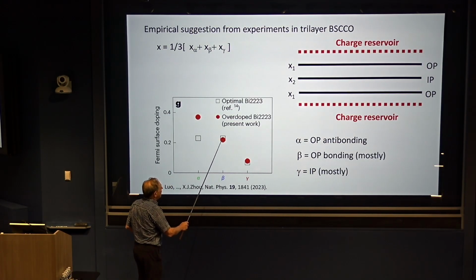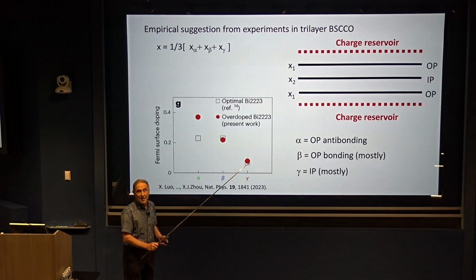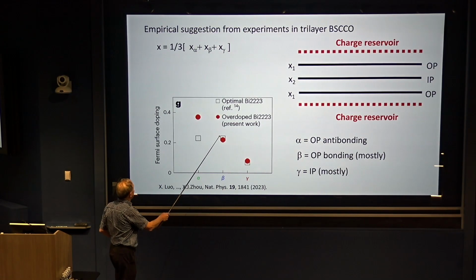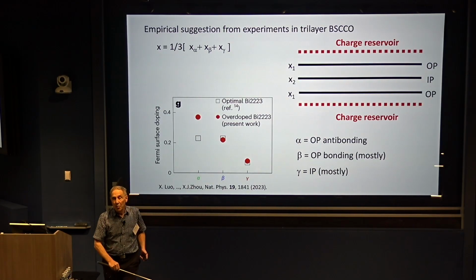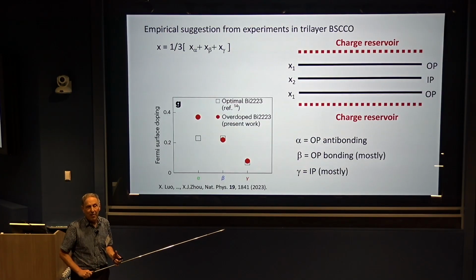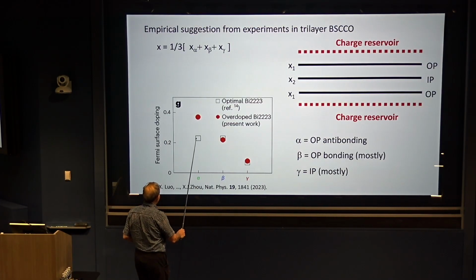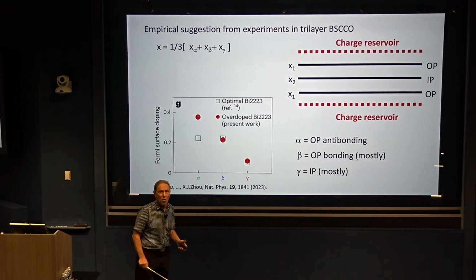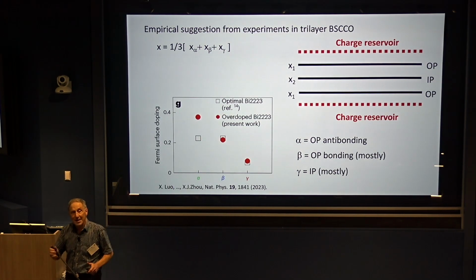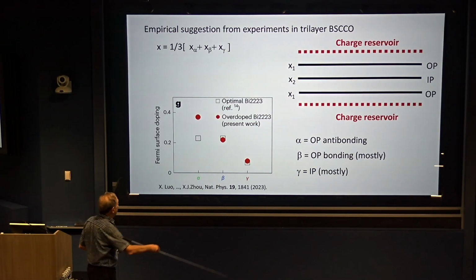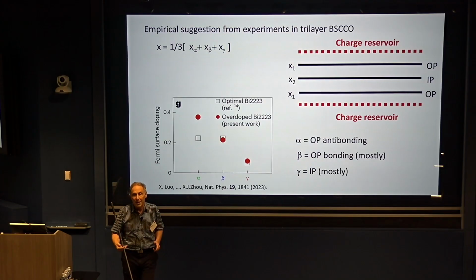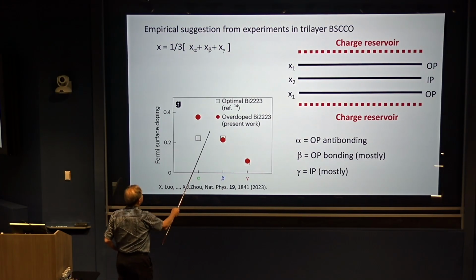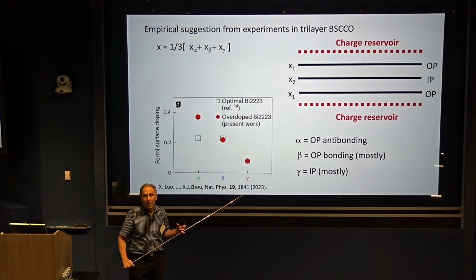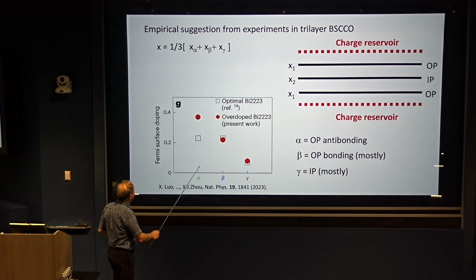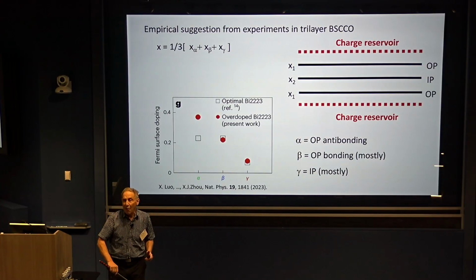And the beta band has a very high doping concentration, about 26%, which again would have a TC by itself that would be close to 0 because it's too overdoped. And the alpha band also, it turns out that in the optimally doped, you can't separate the alpha and beta bands. So within experimental error, they have the same doping concentration. And then the red dots are more recent data on an overdoped sample. And what you see is that the extra doping has gone entirely into the alpha band.